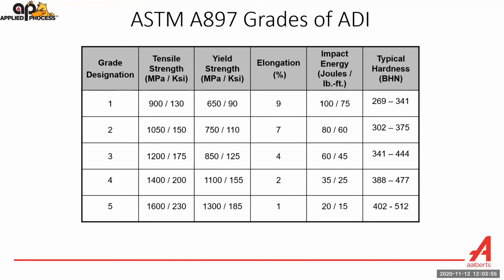There are 5 grades of ADI. 1, 2, 3, 4, 5. This is something that the metallurgists actually made fairly simple to understand. And grade 1 and 2 are typically going to be used in applications where toughness is important. So control arms, knuckles, components that take a shock loading are going to be made out of grade 1 or grade 2 ADI. And there's ISO standards as well as ASTM standards for this material. Grade 4 and grade 5 are higher strength, higher hardness materials, but again, the toughness is lower. Where do we see grade 4 and 5 used? Construction and mining, agriculture. So like ripper points for tilling up a farmer's field will be made out of grade 4 or grade 5 ADI.